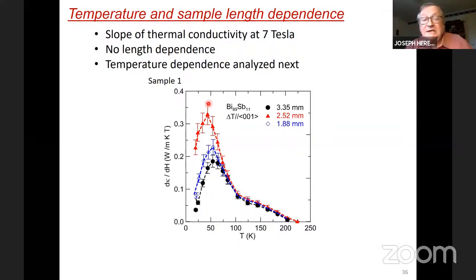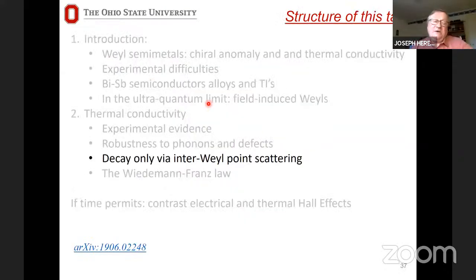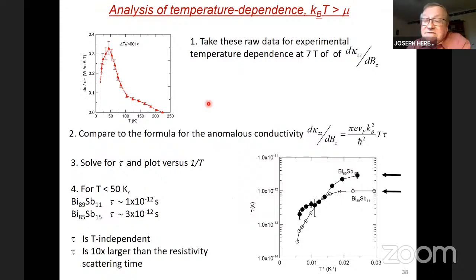Let me then take a little bit further in the analysis of this temperature dependence. And I will try to convince you that the decay with temperature that we observe is solely due to the thermal excitations of carriers from one Weyl point to the other Weyl point and not to phonons or anything else. So here is the analysis I will walk you through.